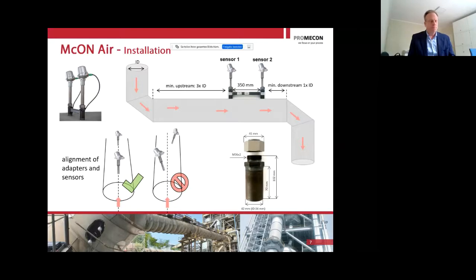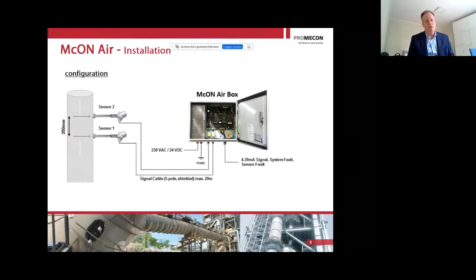Now, I want to let you know a couple of very fundamental advantages of this measurement. As you can see here, you only have a box and two sensors, and what you get is a 4 to 20 milliamp signal or a system fault signal for our measurement. And since our measurement is purely digital, and since we are only measuring time, time is the only variable that we measure, you will not have to recalibrate any drift or any zero span or anything. Our system is calibration free. It is recalibration free over the life of the box.